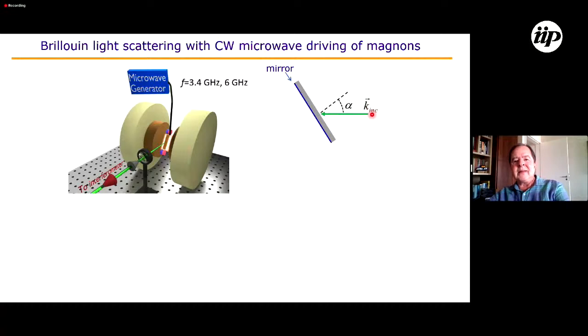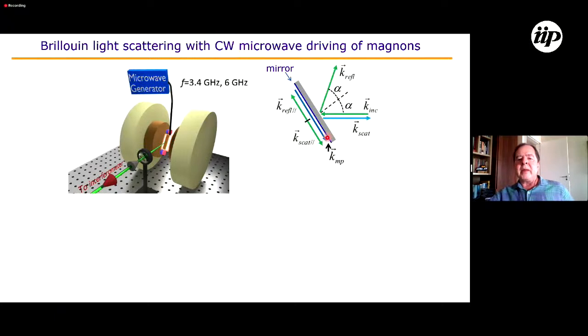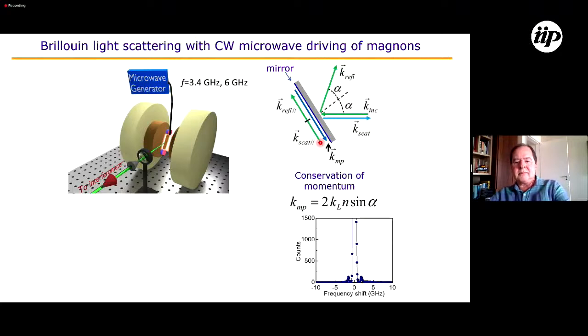Light is incident at some angle with the sample. There is a mirror here, and light is reflected, and we have conservation of momentum in the plane of the sample. So by changing the angle of the sample and the mirror, by changing the angle alpha, we change the momentum of the excitation and of the excited magnon.